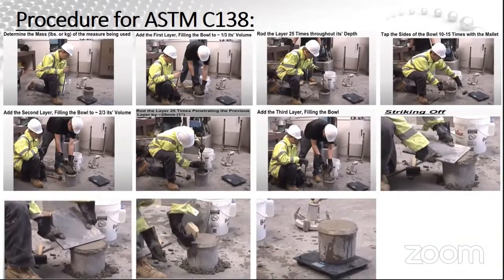The mass of the measure is measured first. The first layer is filled and rodded 25 times and tapped with a mallet 10 to 15 times. This procedure is repeated for the second and third layers. When striking off the excess concrete, press the plate on 2/3 the surface of the measure and with a sawing motion withdraw the plate. Then press the plate to cover back the original 2/3 and with a vertical pressure, you saw in the opposite direction. Then incline the plate and strike several sweeps with the edge of the plate to produce a smooth finish. Clean excess concrete around the measure and determine the mass of the measure filled with the concrete.